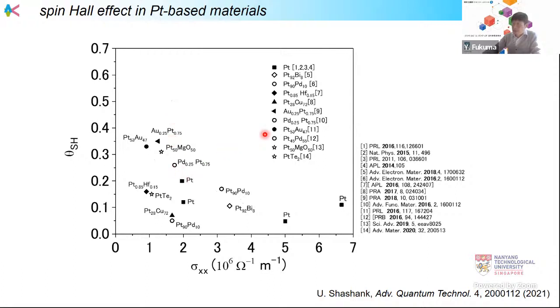Then, there are several reports on increasing the spin Hall effect in platinum by using alloys. For example, by alloying with gold or molybdenum, we can see this kind of enhancement. But the general trend we can see here is that with decreasing conductivity, the spin Hall effect is enhanced. That's why we should enhance the spin Hall effect around here.